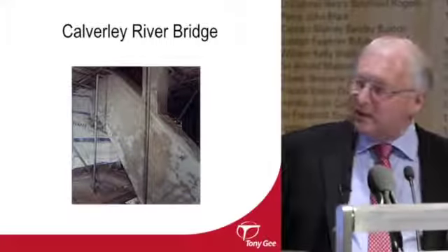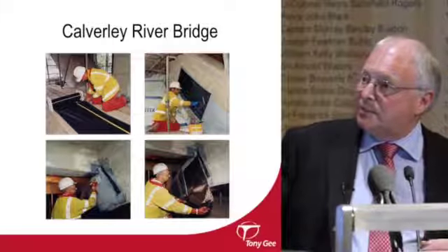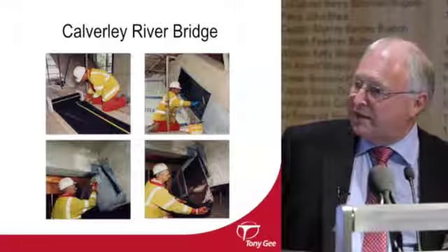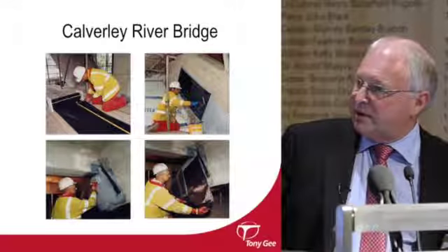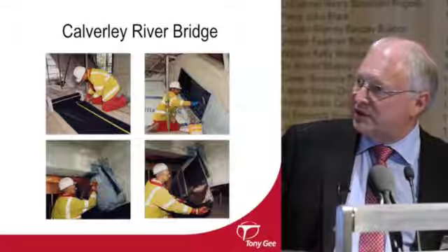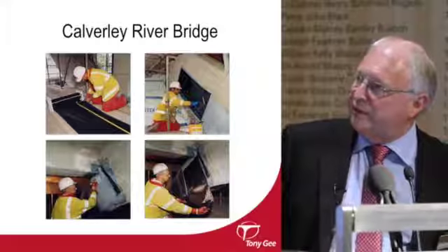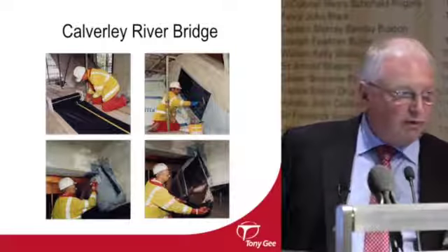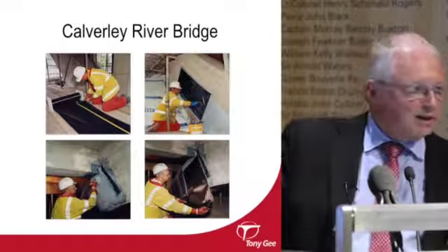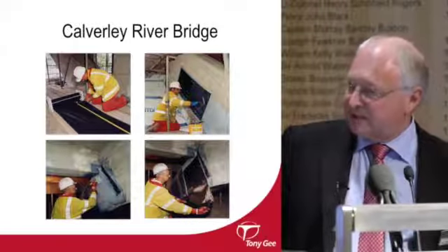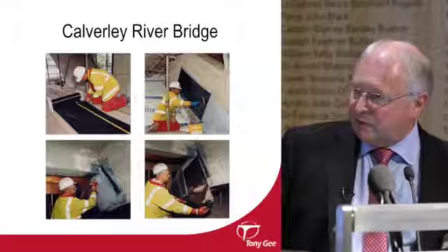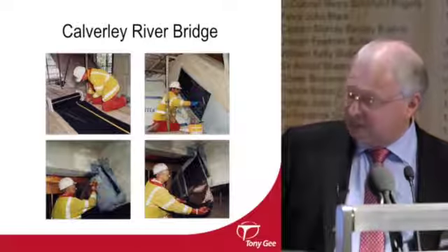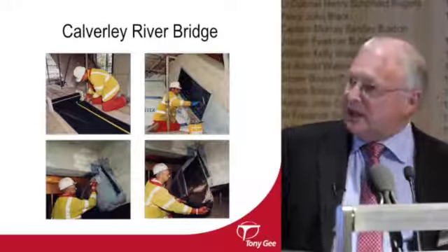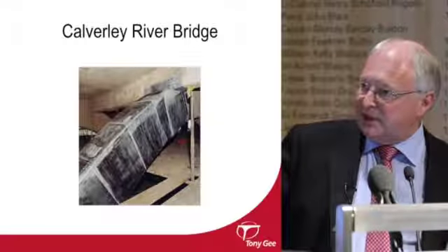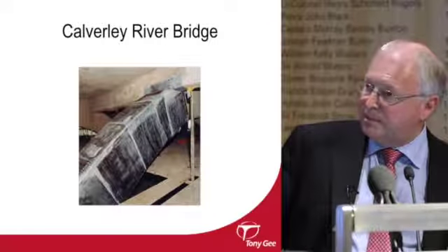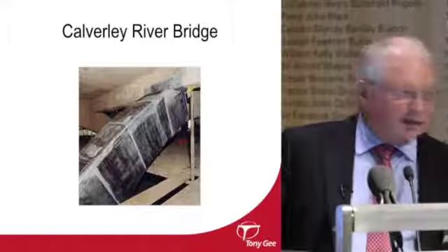And then in this case it was fabric, because we were going to wind this around the arches, brought to site similar to the strips, cut to the right length. This was a dry applied process, so resin, the adhesive, was put onto the structure and then the dry carbon fibre offered up, and you'll see here there are metal washers on the roller, forcing the dry fabric into the adhesive and fully wetting out the composite. Subsequently, further layers of resin were applied by brush, and more layers of carbon fibre. So this was built up by a process known as contact moulding, and ultimately ended up with the arches completely encapsulated with carbon fibre at certain points. And then subsequent to this, there was just a cosmetic layer put on the top to disguise it.